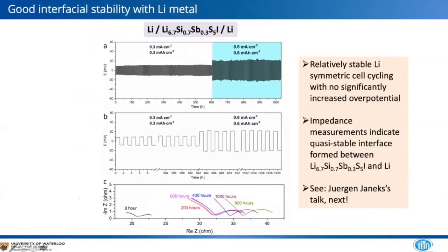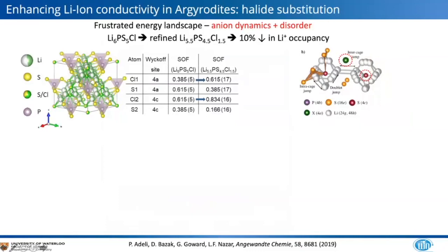So we've also looked just briefly at symmetric cells of this electrolyte together with lithium. And we were able to achieve current densities upwards of 0.6 milliamps per square centimeter over as much as 1,000 cycles. So this again indicates we have a quasi-stable interface formed between this argyrodite iodide and the lithium, likely due to the formation of lithium iodide and perhaps some lithium antimony phases. And Jürgen Janek will be talking more about those interfaces in the next talk.